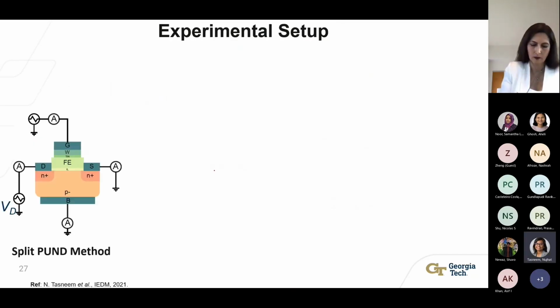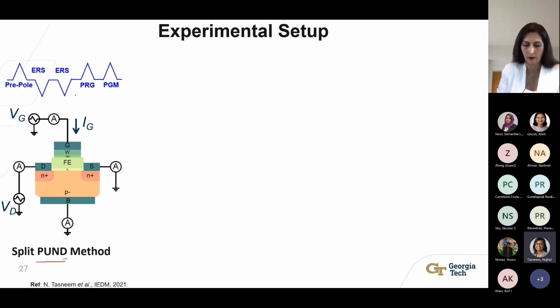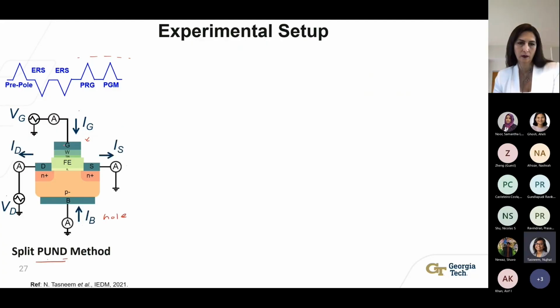In order to do that, we used a technique called split positive up, negative down, or split PUND technique, where we applied a series of triangular write pulses to the gate terminal of the FeFET and directly measured the switching current through all four of the terminals separately. So we did this experiment on an N-type FeFET. The current flowing through the P-type body terminal should represent the majority carriers, or the hole current. On the other hand, the current flowing through the N-type source and drain should represent the minority carrier flow, or the electron current.